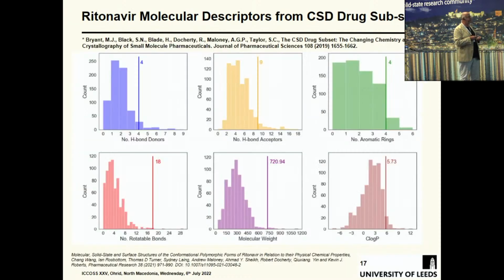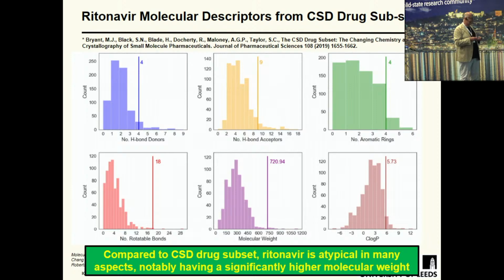It's useful. So let's go back to the pharmaceutical subset, and this is some of the data from the subset in a number of areas: number of donors, number of acceptors, number of aromatic rings, rotatable bonds, molecular weight, and C log P, which is basically the hydrophilic, hydrophobic basis. And you can see where ritonavir sits, always at the edge. This is something one would think about. So compared to the CSD drug subset, ritonavir is even then atypical of many aspects of existing crystal structures, having a particularly significantly higher molecular weight.